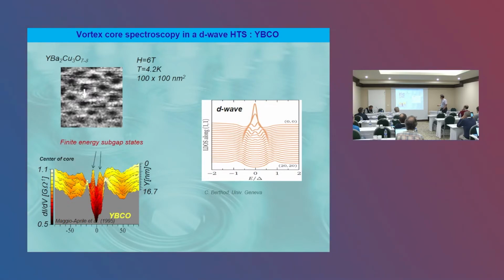So now, the measurements we did in '95 on YBCO, the vortex seen here at a field of 6 Tesla, showed something which was absolutely not expected. The set of two peaks measured at the center of the vortex core was obviously not the one expected, the zero bias anomaly expected at the center of a D-wave vortex core.